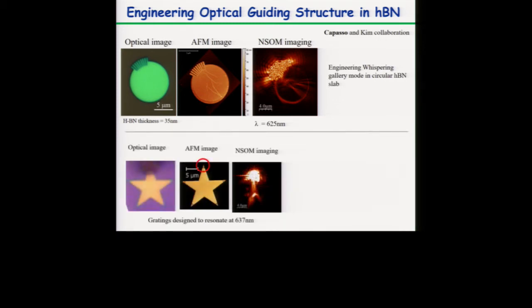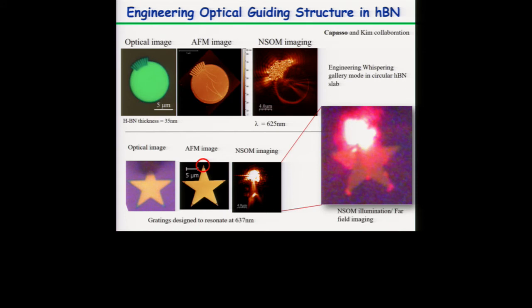We can even make different fancy shapes, like a star. This star has gratings on each of the tips. We can excite at one of the gratings on the tips, and we can collect at another. We can collect light directly at other places on the sample, and we can see that most of the light comes out from these gratings on the tips as well. It's hard to see from this screen, right? Actually it's better here, where we can see the light coming out from these gratings. So we can guide light using a few layers of boron nitride.